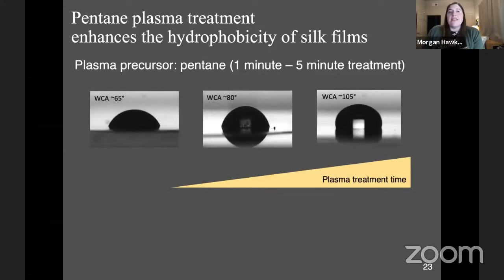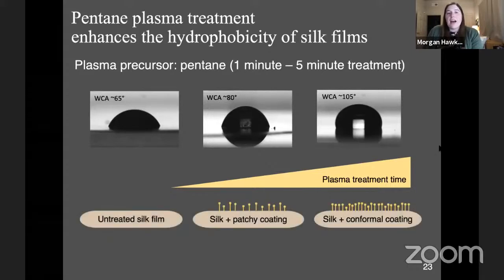What she's found is that increasing the treatment time yields a more hydrophobic surface. So we're looking again at contact angle results for the untreated film, a short treatment time and a longer treatment time. And our hypothesis is that the coating hydrophobicity is dictated, at least in part, by the conformality of the coating, or the uniformity of the coating on the surface that results from the pentane plasma interacting with the surface.